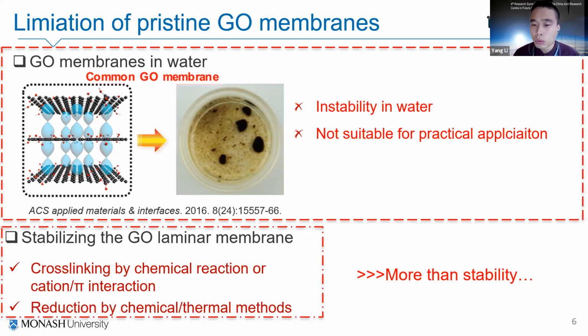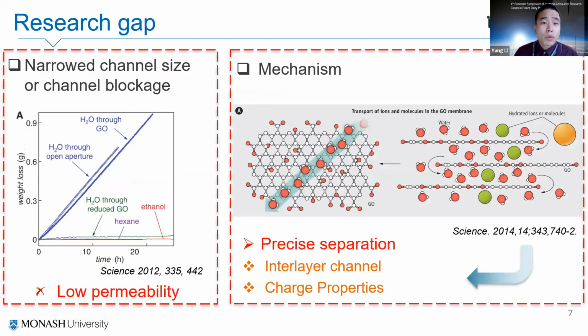But for separation, we do want more than stability. So the research gap is shown here. Generally, after stabilizing the GO membrane, the channel size becomes narrow, and some channels are blocked by the cross-linkers. So it generally results in the membrane showing lower water permeability, and we know precise separation is always the target for different application purposes. So we have to control the interlayer distance and the charge property of the GO membrane.